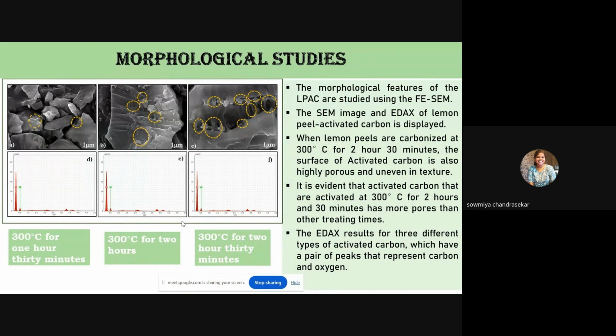FESEM morphological studies reveal that the lemon peel carbonized for 2 hours 30 minutes gives a good porous image, which is shown in the figure. A is 1 hour 30 minutes, B is 2 hours, and C is 2 hours 30 minutes. We can visibly see the porous structure is improved when the sample is carbonized for 2 hours 30 minutes. And below, D, E, F show the EDAX images of these 3 samples, which show the presence of carbon and oxygen.